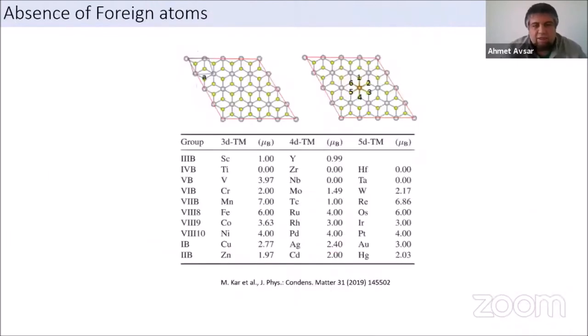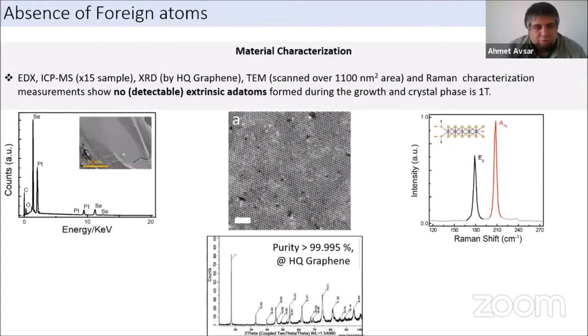Okay, so let me also briefly tell you, there is also a possibility of having a magnetic response in platinum diselenide if you have some foreign atoms. There were some predictions, calculations, saying that if the material is doped with transition metal atoms, then you might have magnetism. So the question was, is it possible that our materials are contaminated with foreign atoms, and that's why we see this magnetic response? We worked very hard to exclude this. Indeed, we did a lot of TEM scanning and XRD, EDX, ICP-MS, and Raman characterization, and we couldn't detect any extrinsic atoms. So we do believe that the origin of this signal is coming from the defects in platinum diselenide, and we also believe that it depends on the concentration of these defects.